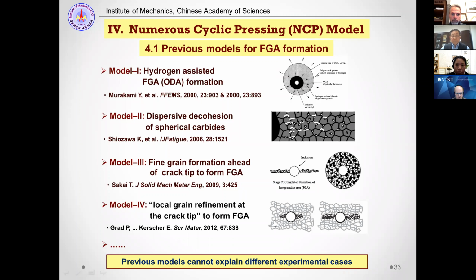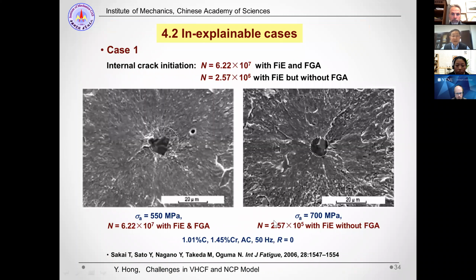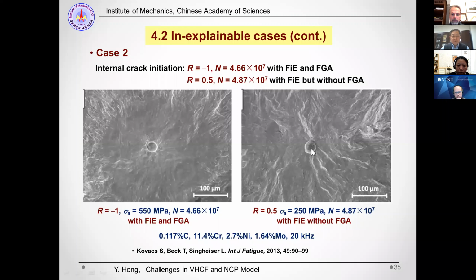For example, for the case of 10 to 7 cycles loading, the FGA and the rough fracture surface are quite evident, but for the loading of 10 to 5, there's somehow smaller loading cycles. The FGA morphology is not such kind of rough surface of FGA. So for different loading cycles, the morphology can be different. And for different loading stress ratio, also may have different morphology. For -1 stress ratio, the rough surface of FGA is evident, but for 0.5 stress ratio, the FGA cannot be observed. It's not FGA morphology.